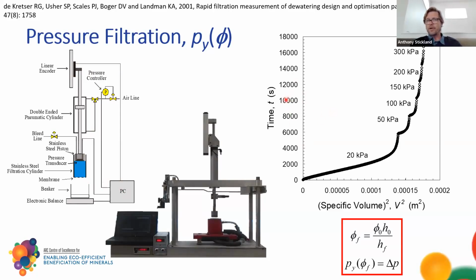An example of some results, this is for a stepped pressure compressibility test where we compress it at one pressure until we reach our equilibrium criteria, and then compress it at higher and higher pressures. And from the endpoint at each of these, we assume that that's reached equilibrium, and from that we get our compressibility curve. That's just the conversion there.